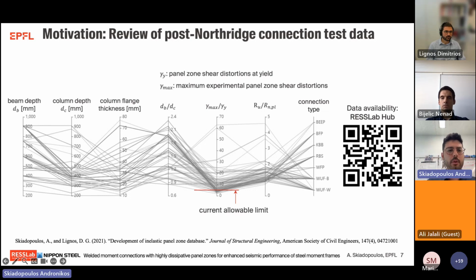If we look at the fifth column of this parallel plot that concerns the panel zone response, we see with gamma max over gamma y the attained panel zone shear distortions normalized by the panel zone shear yielding, noted in this presentation as gamma y. And what we see here is that this database collection that we have includes panel zones that far exceed the current allowable limit. And therefore, we can study the effect of inelastic panel zone shear yielding in the connection performance.